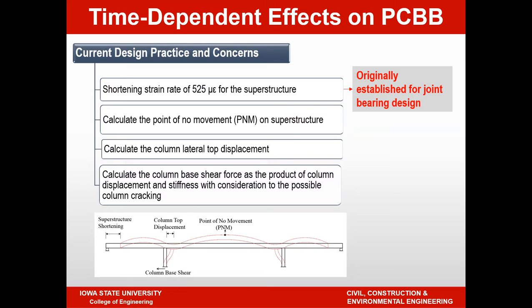The 525 microstrain I mentioned was originally developed based on bearing designs. So for joint bearing designs, some assumptions were made, and this was not specifically designed for the type of problem that we have dealt with, and therefore it's important to verify that number is appropriate. Ignoring the concrete relaxation or assuming all of the columns will crack may underestimate or overestimate the design forces, and that's something we want to make sure gets captured as accurately as possible.